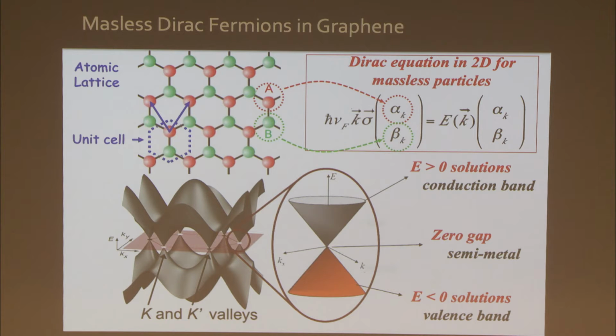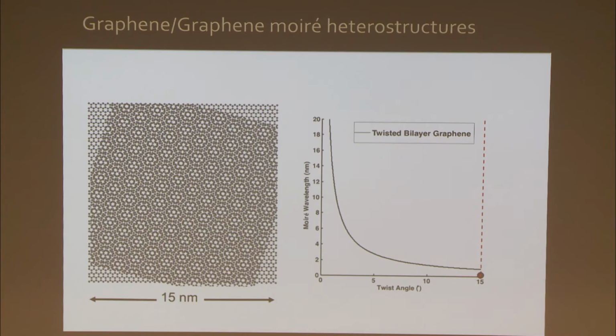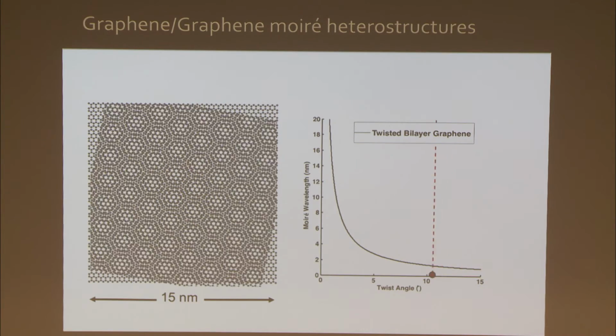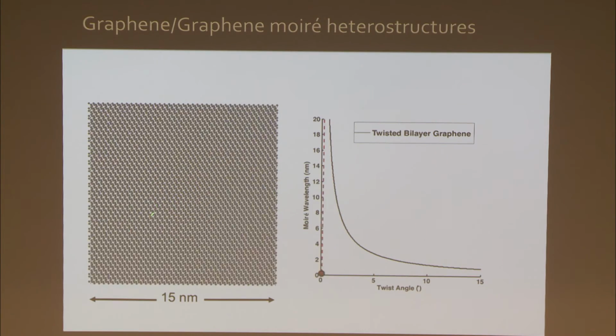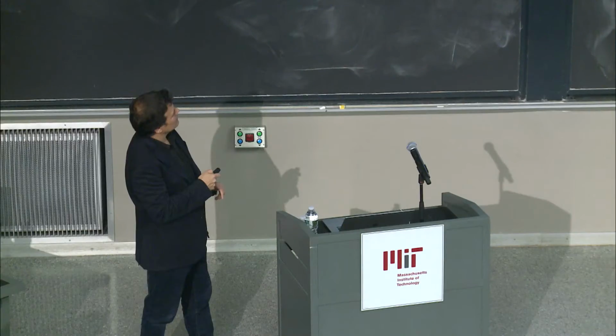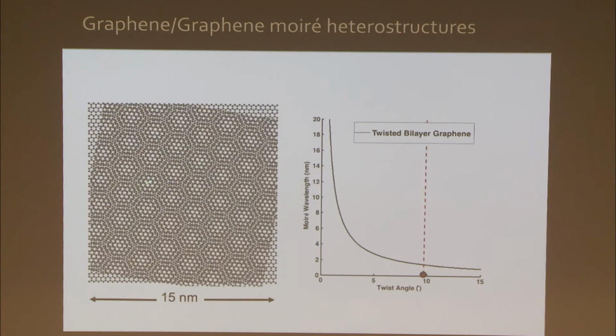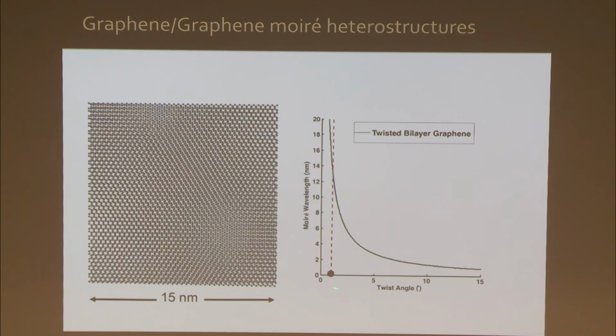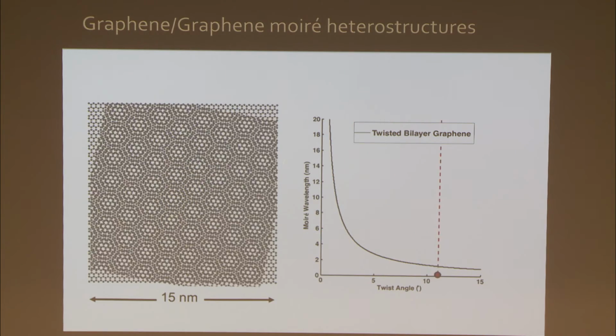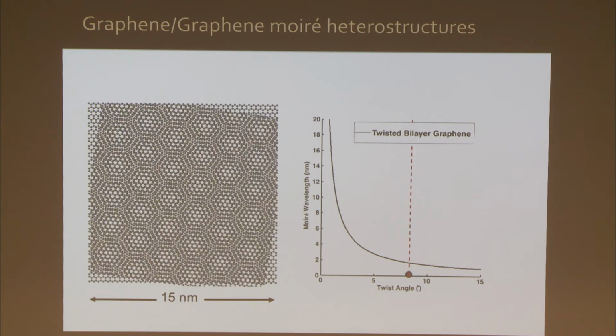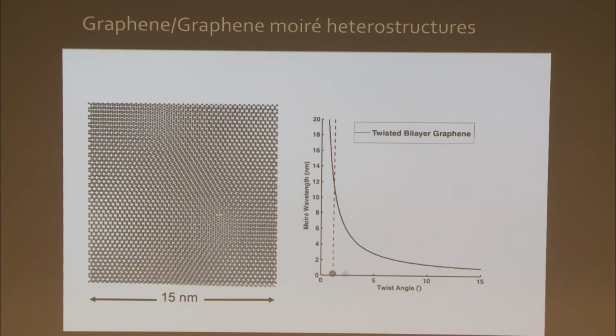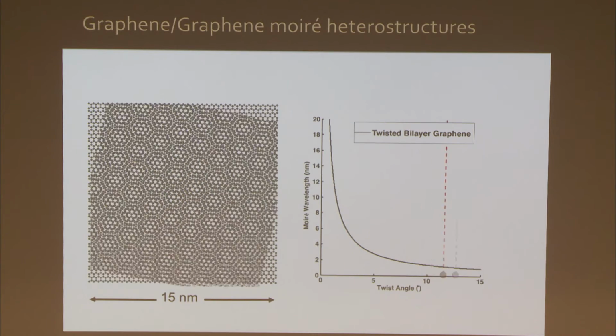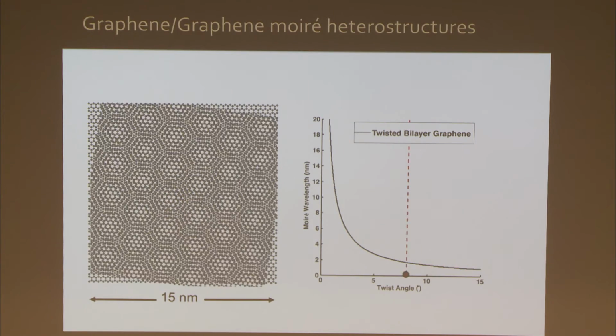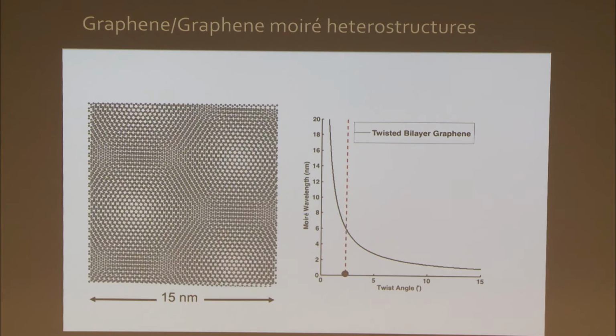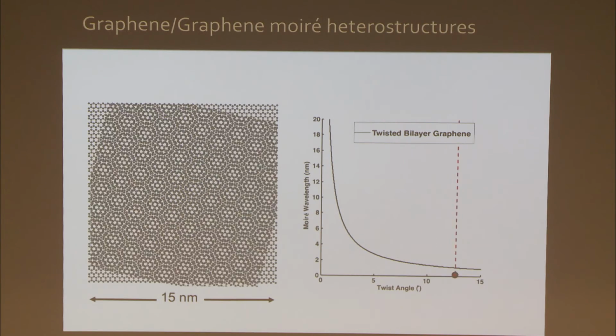Now, this is the electronic structure of graphene. What happens if you put graphene on top of graphene and you rotate it, okay? So if you do this in real space, what happens is that you form a Moiré pattern where the Moiré wavelength, which is the distance between the soccer balls that you see here on the screen, roughly goes as 1 over the twist angle for small twist angles. Okay? So now, this is what happens in real space. Let me show you now what happens in momentum space and therefore what happens to the electronic structure.